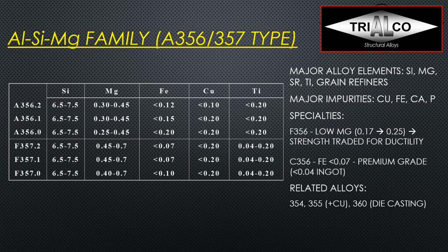F356 is actually a very low magnesium version of the 356 family, for basically high strength that's traded in for ductility. Another oddity is the C356, and that is a premium low iron 356 variant, and the ingots are usually required to have below 0.04 iron. Related alloys here would be the 354 and 355. They add a little bit of copper, or the 360, which is a die casting variant.